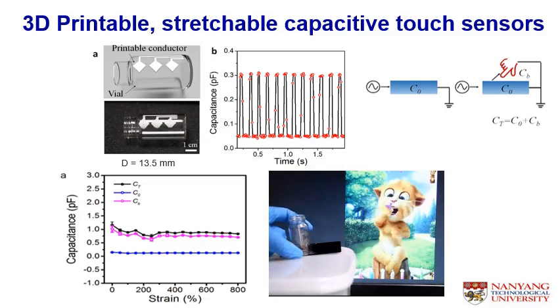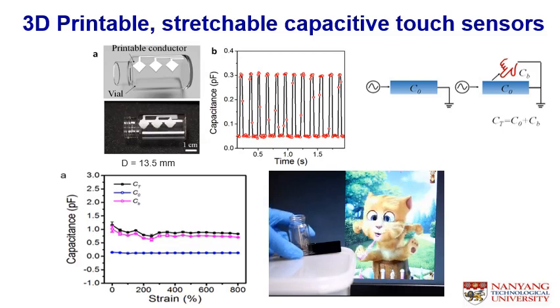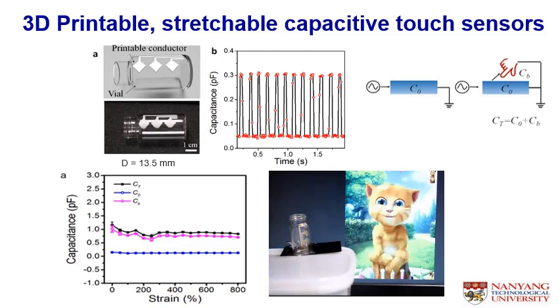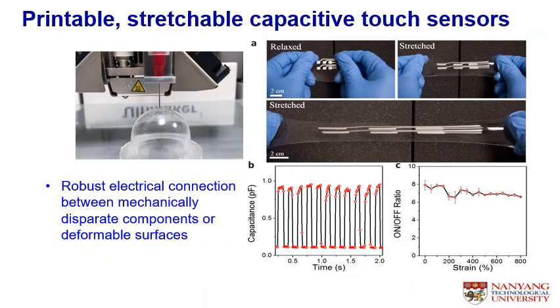In one of our work, we have demonstrated development of materials of suitable viscoelastic property for 3D printing using DIW. Over here, a capacitive touch sensor is being demonstrated using a 3D printable conductor onto curved substrate. As we can see here, the capacitance is stable as a function of strain up to 800%. This allows us to achieve a stretchable capacitive touch sensor using 3D printing. The on-off ratio of the capacitive sensor is relatively stable as a function of strain. This is because of the robust electrical connection between the mechanical disparate deformable surfaces.